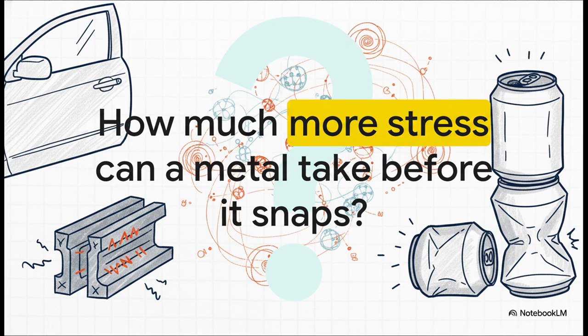Which leaves us with a totally fascinating and highly practical question to ponder. Every single time we shape a car door, forge a steel beam, or draw an aluminum can, we are packing up to 10 billion defects into every square millimeter, trapping 5% of our massive deformation energy as permanent internal tension. With all that microscopic strain silently screaming inside the atomic lattice, how much more stress can a metal realistically take before the entire system fails and the material finally snaps?